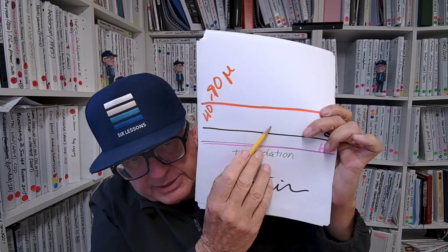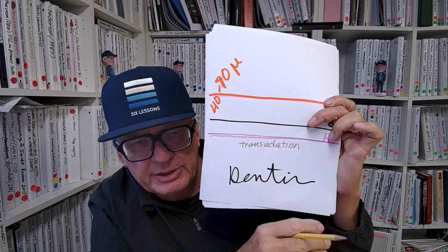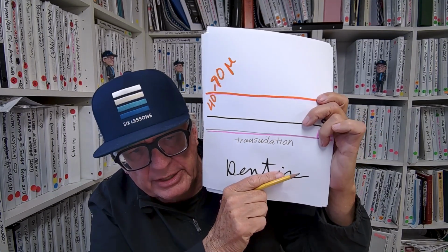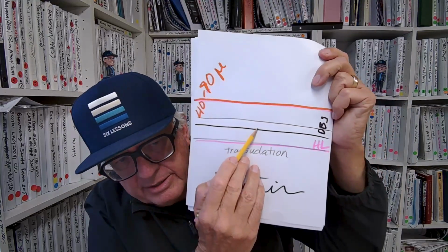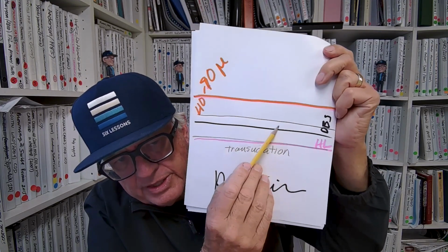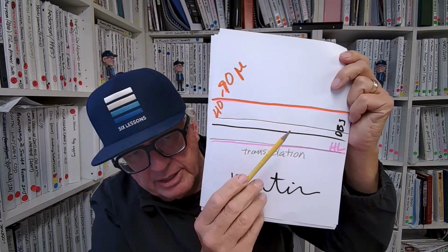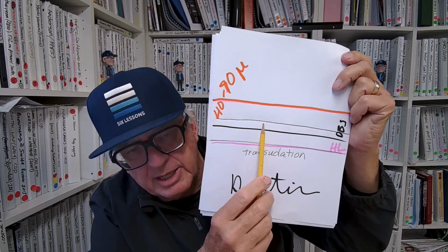But then on top of this, this layer is polymerized, but a polymerized resin that's using camphorquinone for its initiator. The camphorquinone is quenched by oxygen. So this layer of the dental bonding system right here, if this is too thin at 10 microns, when you put the light on it, the whole layer does not polymerize.